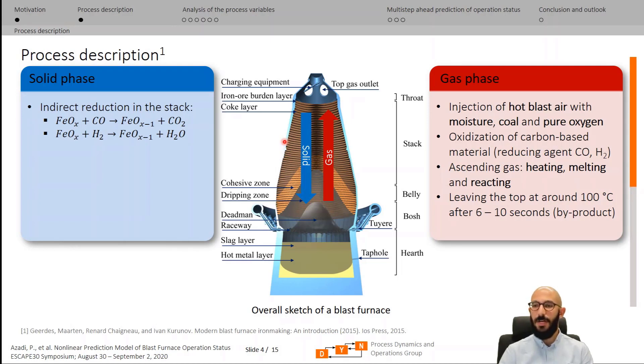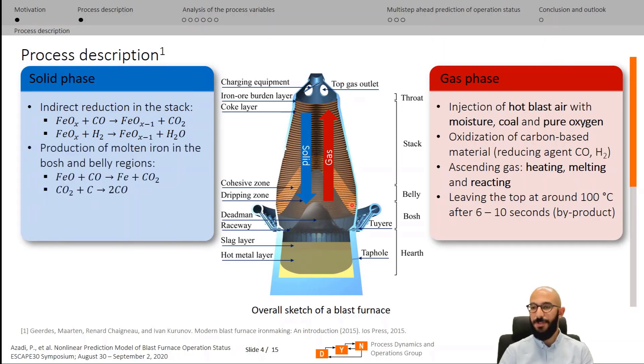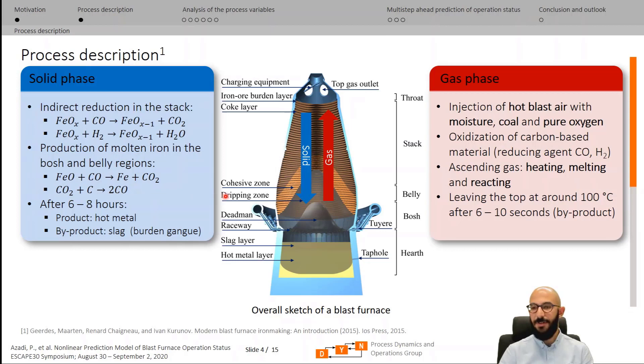In the solid phase — the iron ore burden and coke layers — solid components are first heated up to around 600 degrees Celsius, at which the iron ore goes through indirect reduction reactions in the stack zone, reducing higher iron oxide to lower iron oxide wustite. Descending further to the high-temperature regions of belly and bosh, the molten wustite goes through direct reduction reactions producing molten elemental iron. After 6 to 8 hours, dripping through the active carbon zone — the dripping zone — and accumulating in the voids of the inactive carbon region — the dead man — the hot metal is periodically tapped out from the bottom through tap holes at temperatures around 1500 degrees Celsius.